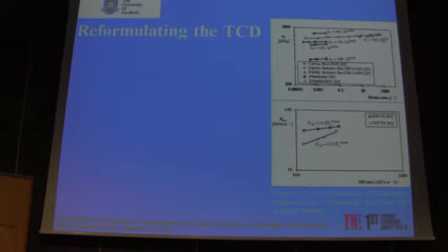Figure 3 plots on a log graph the dynamic failure stress and the fracture toughness against the strain rate and the stress intensity factor rate. If we use Z dot to denote the loading rate, strain rate, displacement rate, or stress intensity factor rate, we can simply get the mathematical law as shown. These two figures clearly support the idea that the selected material data can be described by a power law.